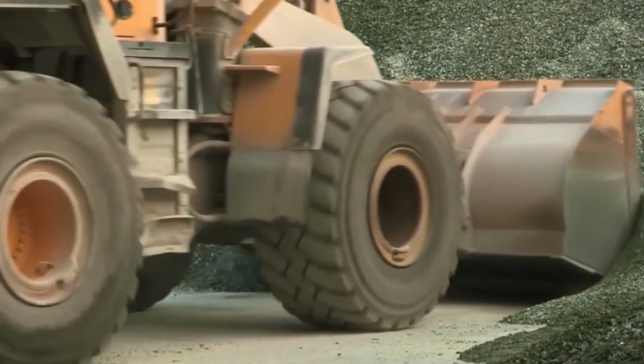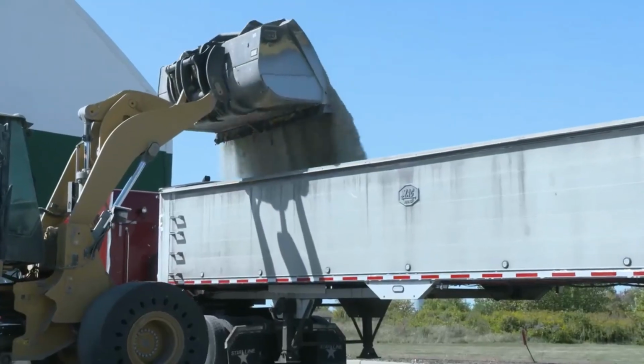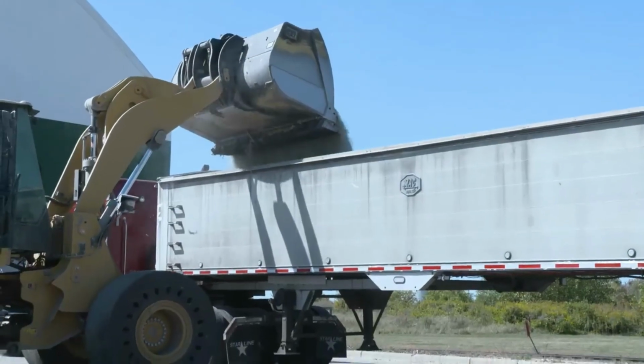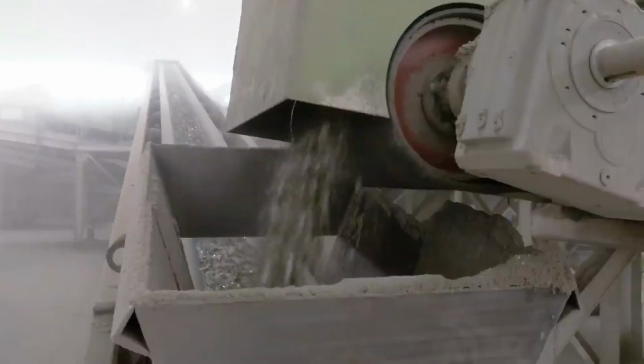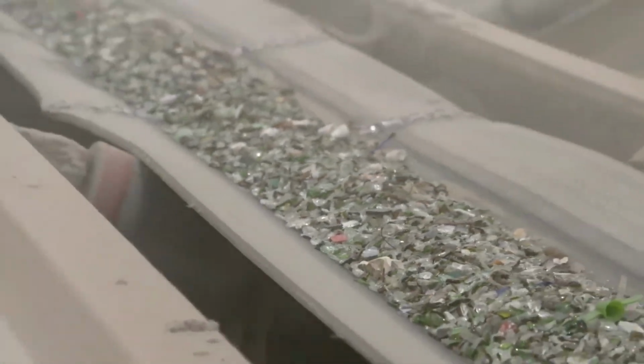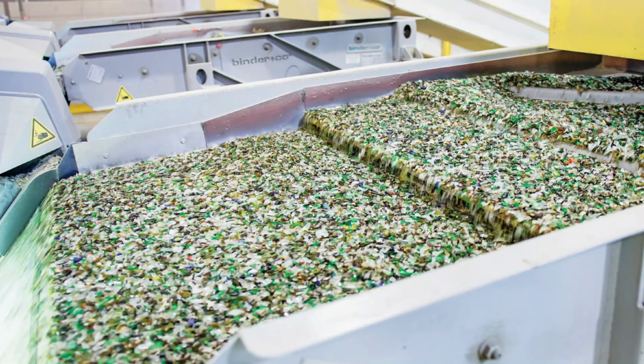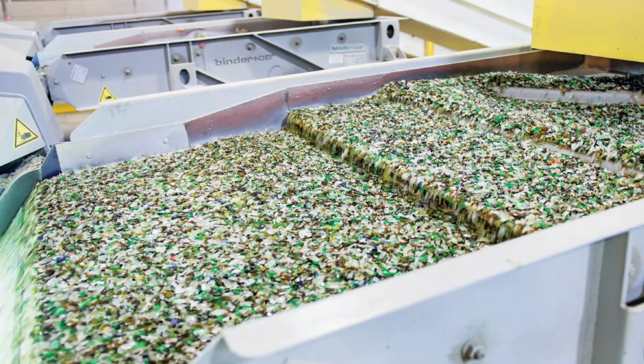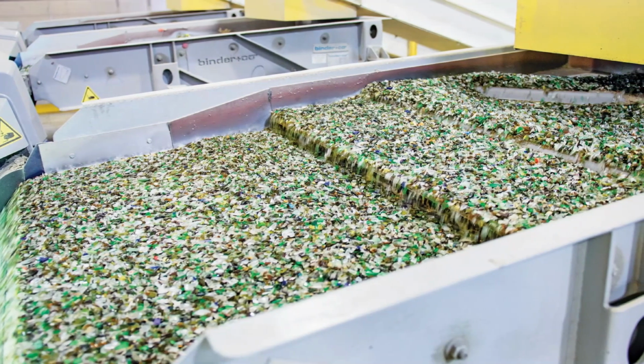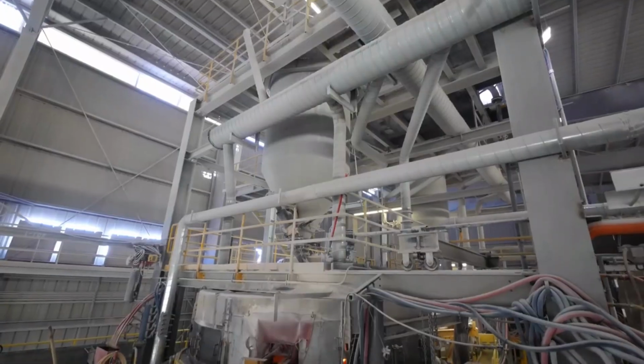But the most important part is still the cullet, which can make up 20 to 70% of the batch. This helps the melt flow faster and cuts energy use by up to 40% compared to brand new raw materials. In fact, adding just 10% more cullet can reduce energy consumption by about 3% and significantly lower CO2 emissions. Once all the ingredients are carefully measured and mixed according to the factory's formula, the blend is ready for the furnace.